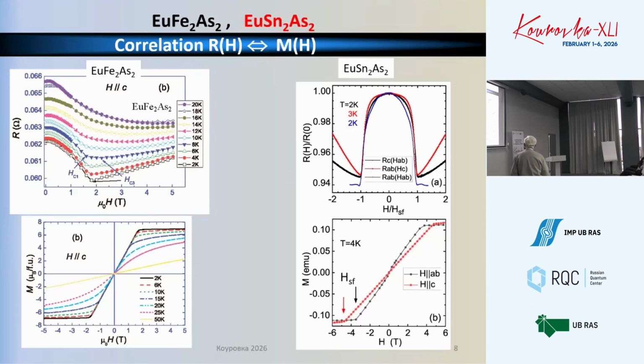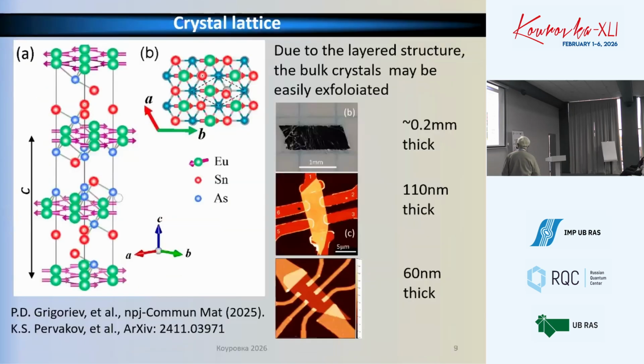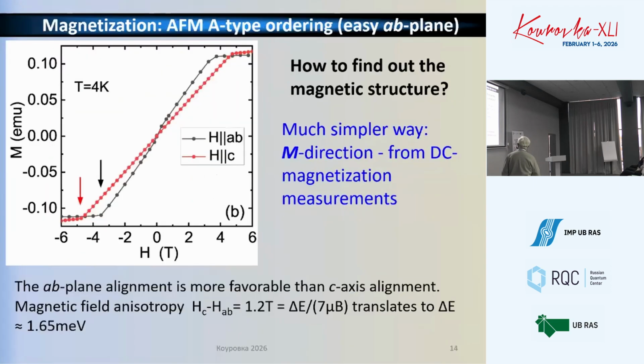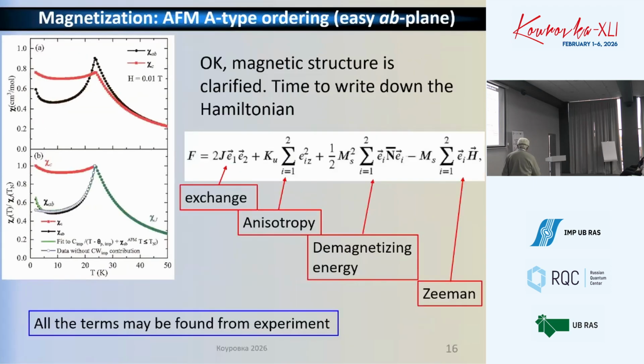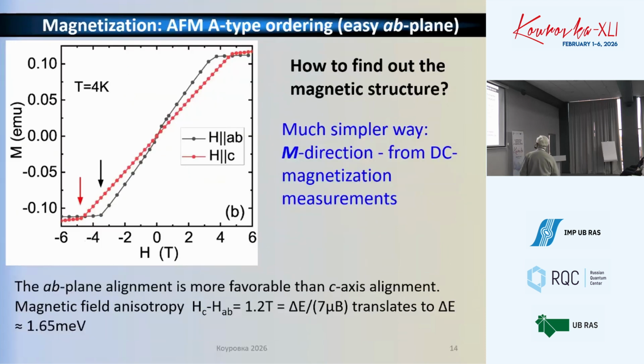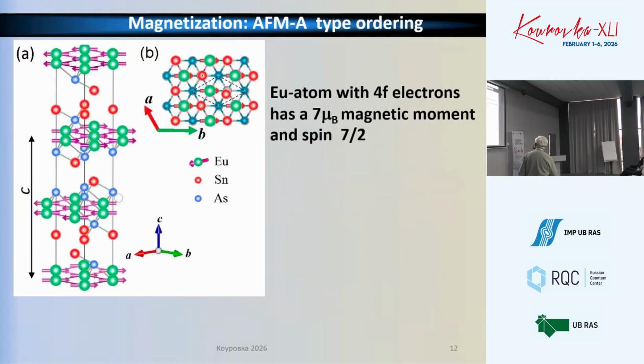This is important. But what puzzled us when we first started studying this material, there is a tiny but still pronounced magnetoresistance. It's negative magnetoresistance. Further, I don't show the magnetoresistance transformed to quite usual orbital type, omega c tau squared, just a positive magnetoresistance, where there's no puzzle. But this one is quite surprising. It is present in almost all of the materials of this kind. I will show you, or maybe later on, but just do believe me that this is typical for the wide class of these materials. So some strange negative magnetoresistance.